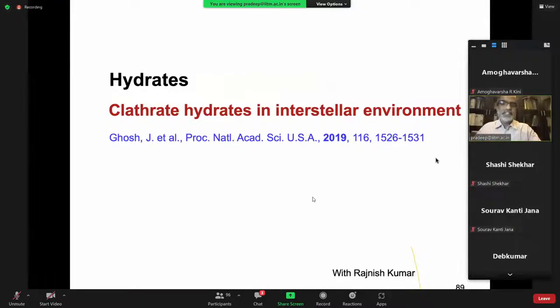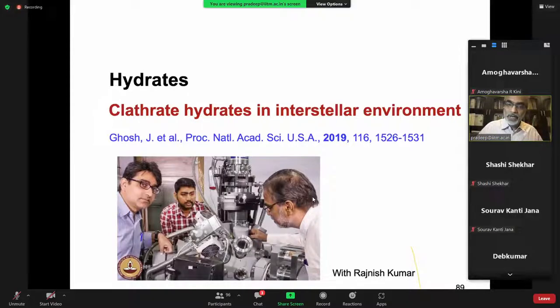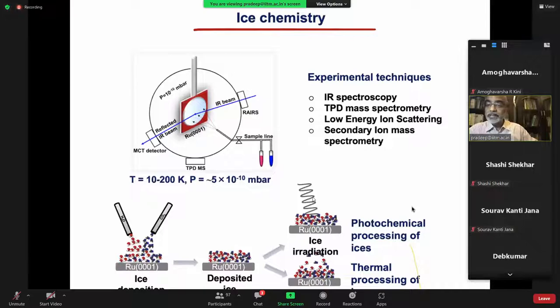Having come to the end of this cluster story, let me tell you one or two things very exciting. So we have been studying gas hydrates with Rajneesh Kumar. We detected methane hydrate even at 22 Kelvin. Carbon dioxide hydrate, even at 10 Kelvin. Very interesting from an interstellar point of view. But very recently, Gaurav has done this interesting experiment in UHV. Here is a ruthenium single crystal, and you put water and carbon dioxide on the surface and control the conditions, temperature, etc. We do infrared spectroscopy, temperature programmed desorption mass spectrometry, low energy ion scattering, secondary ion mass spectrometry, all of these in this chamber at 10 power minus 10 millibar, at 10 Kelvin or 7 Kelvin. And that's the limit of our instrument.